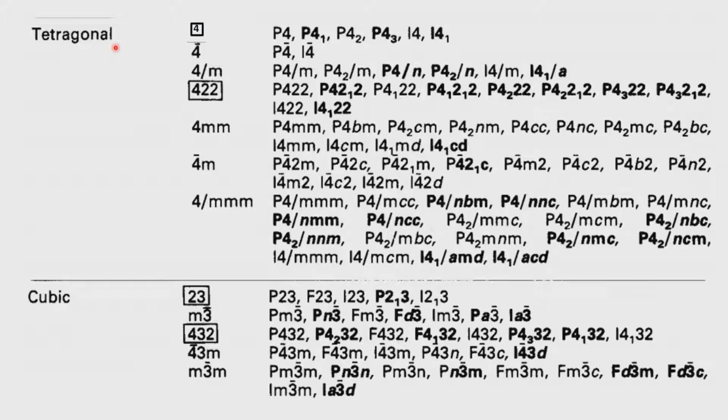At the same time, if the base is square, then the other two perpendicular directions are independent of each other, and therefore the only possibility of having other than a primitive lattice for the tetragonal system is the body center. So for a tetragonal system we will not get the A, B or C face centered space groups, because a equals b decides that we cannot have this, and this is the case which we should remember.